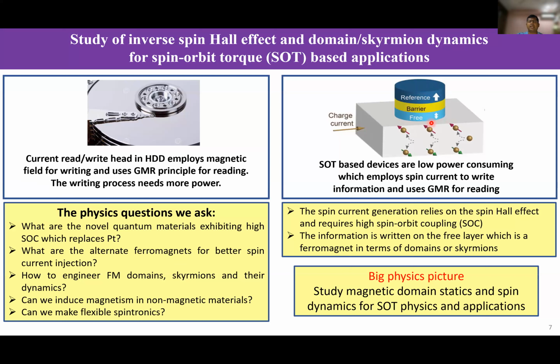And basically, the idea is if you change the magnetization orientation of this bottom layer, you can define parallel and anti-parallel orientation. Basically, you can read it as 0 or 1, because when you read it, it will give you low or high resistance, which you define as 0, 1, just like in the GMR. Okay, but the whole difference to the current technology is you don't employ any magnetic field. That's the most significant difference.